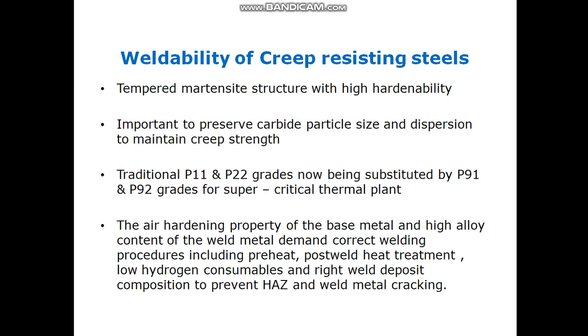This Cr-Mo steel has air hardening property. Due to their high alloy content, their weld metal demands correct welding procedures that include preheating, post-weld heat treatment, low hydrogen consumables, and right weld deposit composition to prevent heat affected zone and weld metal cracking. So for Cr-Mo steel, practices like preheating, post-weld heat treatment, use of low hydrogen consumables, and right weld deposit composition are very much necessary to prevent heat affected zone and weld metal cracking.